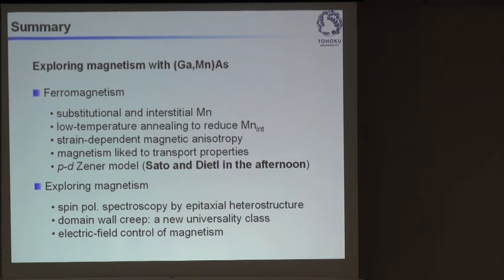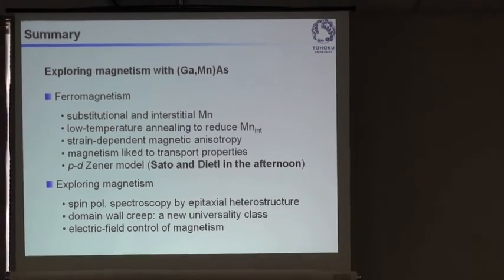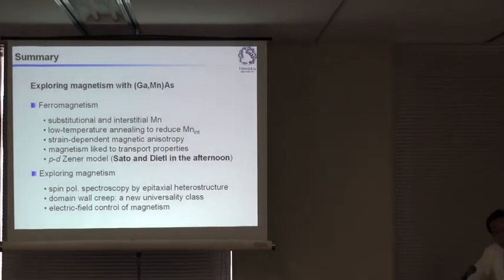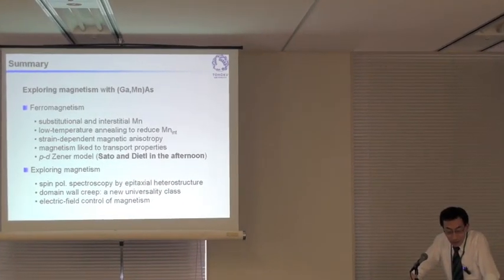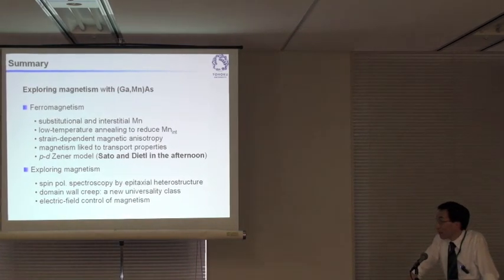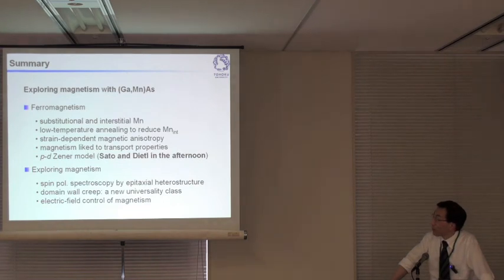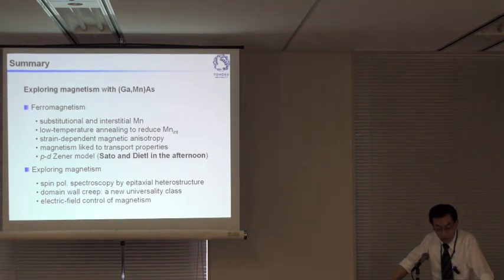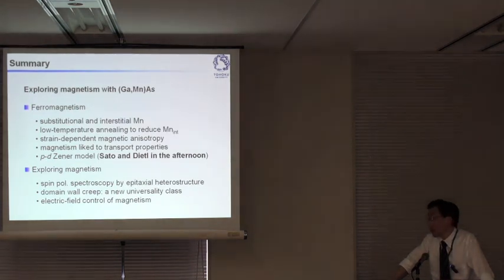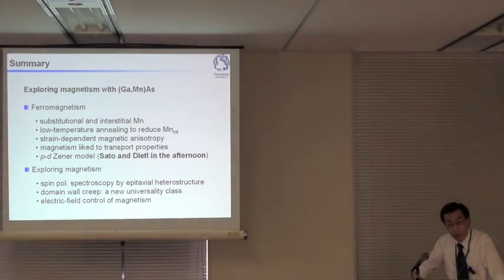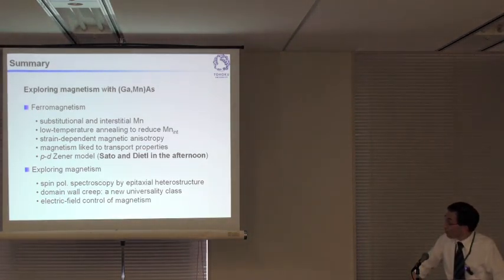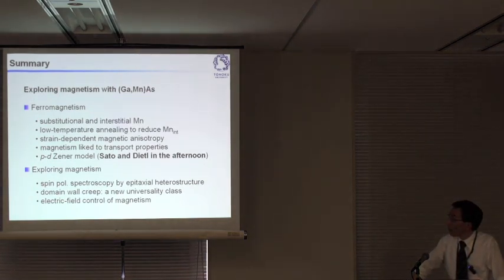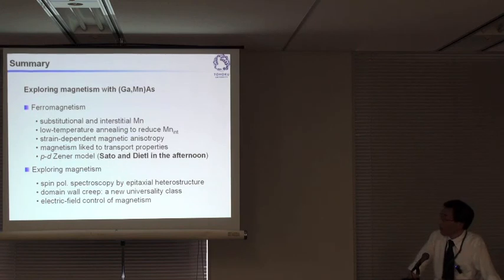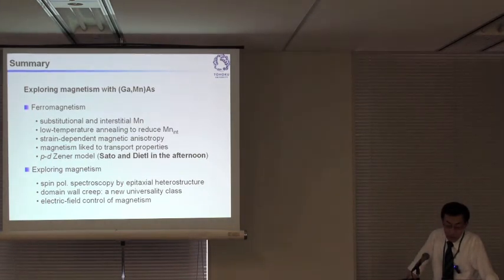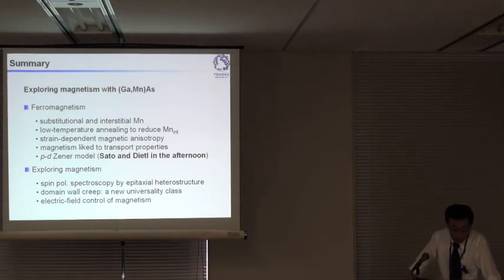I have shown you three examples. By using this ferromagnetic semiconductor, we have explored a number of new dimensions of magnetism. One is that by taking advantage of the fact that we can grow gallium manganese arsenide epitaxially on top of non-magnetic heterostructures, we can use it, for example, to do energy-resolved spin polarization spectroscopy. Or we can explore domain wall creep motion. And because of the low magnetization, we have been able to see spin current induced domain wall creep and found that it belongs to a very different universality class of domain wall creep motion.